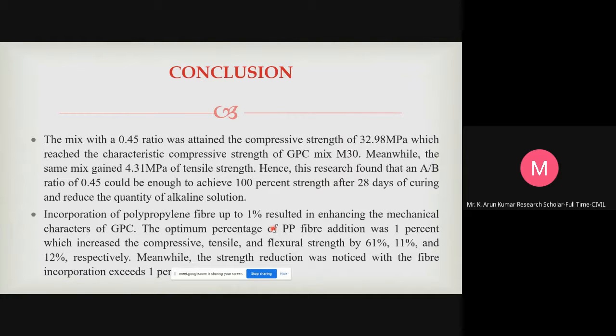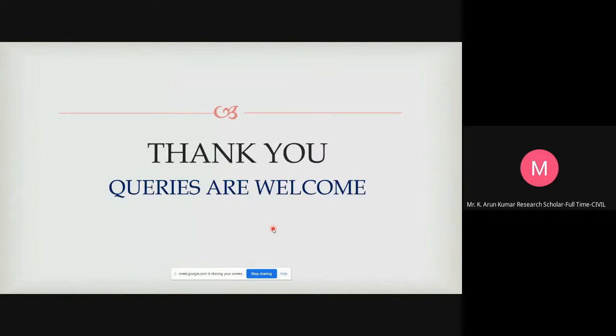And finally, in the optimization of polypropylene fiber, 1% of fiber has obtained the optimum strength. Hence, it can be chosen, and the 1% addition of fiber can improve the tensile, compressive, and flexural strength by 61%, 11%, and 12% respectively. Beyond the 1% addition of fiber, the strength reduces in all strength characters. Hence, 1% can be chosen as optimum.